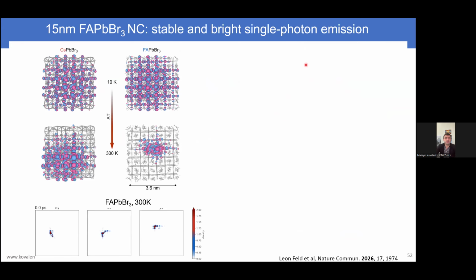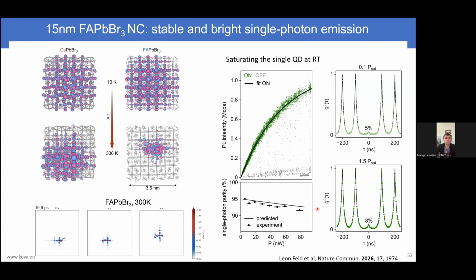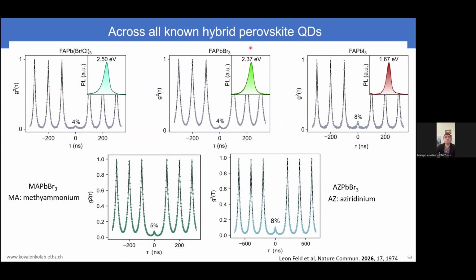And so what he did, he simulated this wave function localization of holes in this case, and he could show that your basically exciton is not permanently localized anywhere, it moves around. So it is normal Wannier-Mott exciton, but it's dynamically localized. And that is a hypothesis why the Auger-Meitner recombination is greater in these materials, and you can drive these emitters at room temperature to basically saturation while maintaining good single photon purity at low excitation fluencies and also at high excitation fluencies. And that is true also across all hybrid perovskite quantum dots.